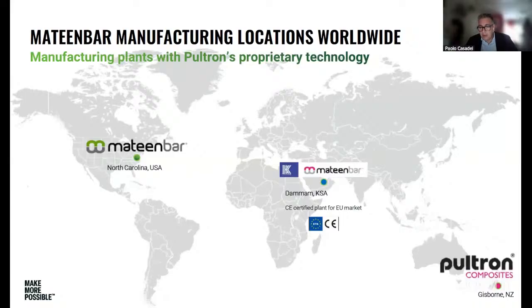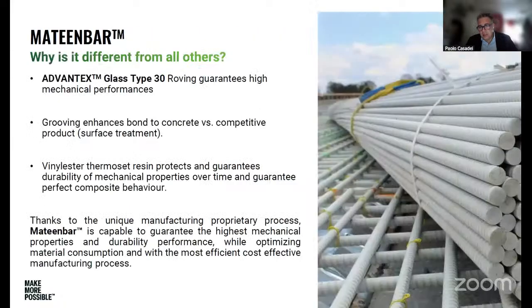The specific technology of how we manufacture these rebars was developed in New Zealand, and you can see here pictures from real job sites. Again, there is a glass roving, which is our Advantex Glass Type 30. Then, to enhance the bond between the bar and the concrete, because steel rebars are ribbed, in our case the roughness is provided by mechanically grooving the bar. And then we have a thermoset vinyl ester resin.